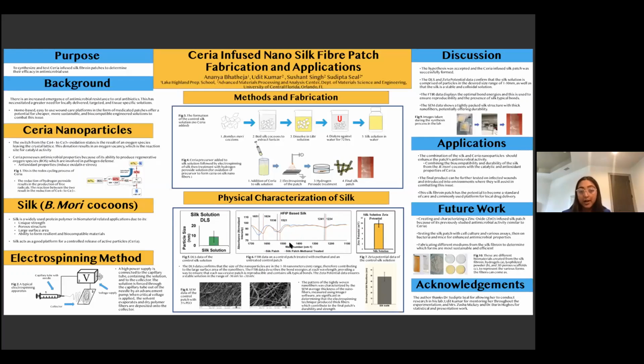And then through the FTIR, we want to see a couple of things. The first thing is that the bond energies are matching previously published data to confirm the reproducibility of the silk. What that means is that we check the bond energies at each peak, at each trough. We're essentially checking that these silk fibers, this is silk, this is not some other material. We're forming the right silk. And the second thing is that at the peaks and the troughs, you can see the wavelength, and that shows you, again, that beta sheet conformation, which is very important to this project.